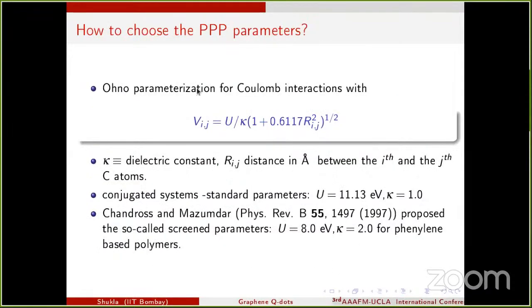The parameterization for the long-range Coulomb interaction is done in terms of three parameters, actually, or one could say two. One is Hubbard U, which we have to choose. Then the second one is kappa, which is like the dielectric constant of the medium. And then we have Rij, the distance between the two carbon atoms in angstrom units. We have a standard set of parameters which were initially proposed by Ohno, and there one takes U equal to 11.13 eV and kappa equal to 1.